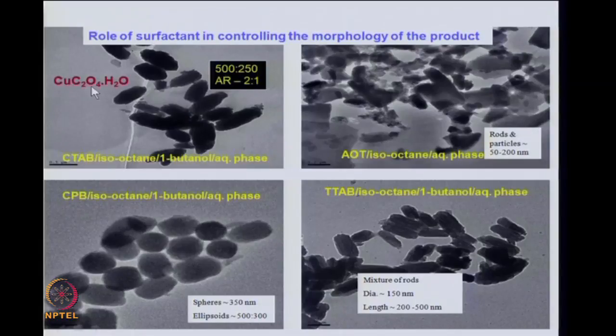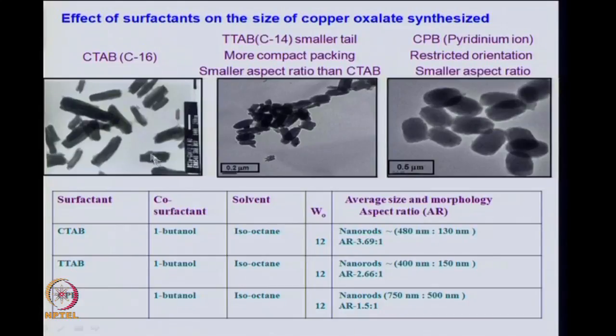Earlier we showed nickel oxalate, this is copper oxalate, where you have changing the surfactant from C-tab, which is a cationic surfactant, to AOT, which is an anionic surfactant. And then this is again a cationic, but it has a restricted rotation because you have a pyridinium group here. So, this is cetyl pyridinium bromide, whereas this is cetyl trimethyl ammonium bromide. And you see the shape of these particles are not so rod like compared here, they are more spherical. However, if you use another surfactant like TTAB, of a different dimensions, different chain length, you get again rod like structures. So, the surfactant has a very important role in controlling the shape and the size of these particles.